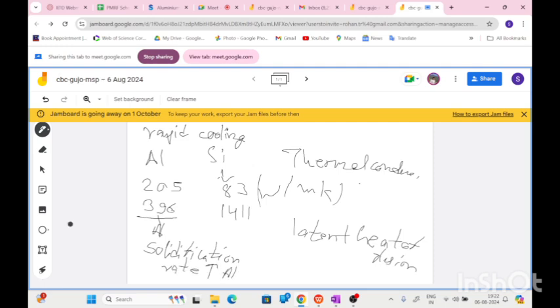In aluminium, what happens if there are two edges, first aluminium, this is silicon, and next is the aluminium? The aluminium will grow faster, and eventually it will entrap the silicon plate or silicon nuclei, and the silicon growth will stop. So by rapid cooling also we can modify the microstructure and increase the ductility of the aluminum silicon alloy.